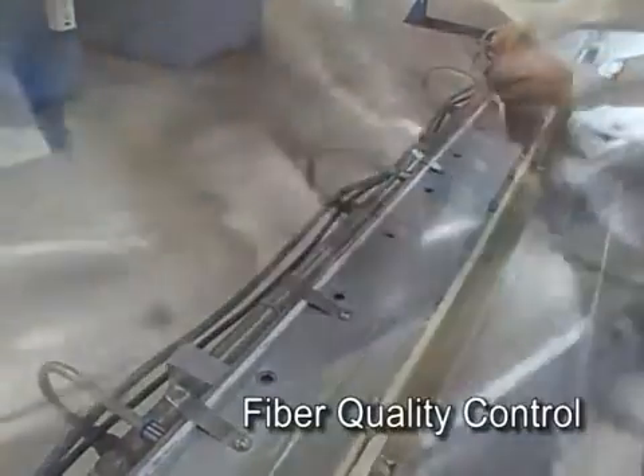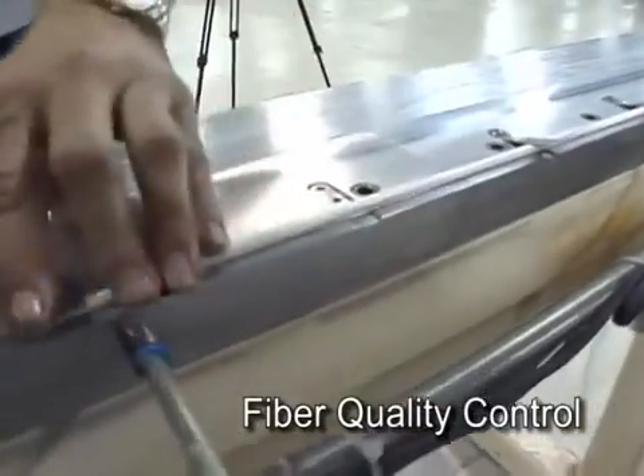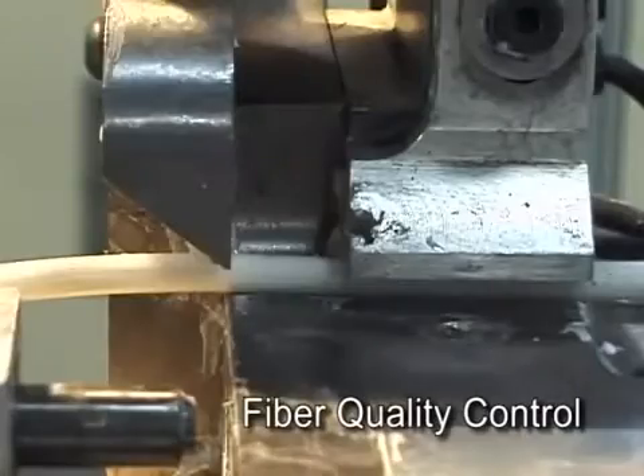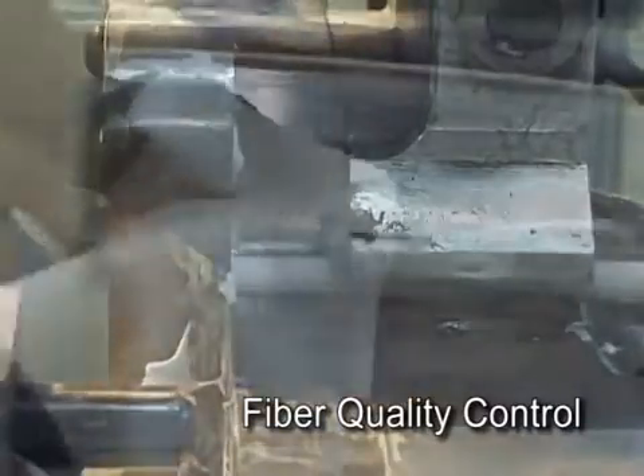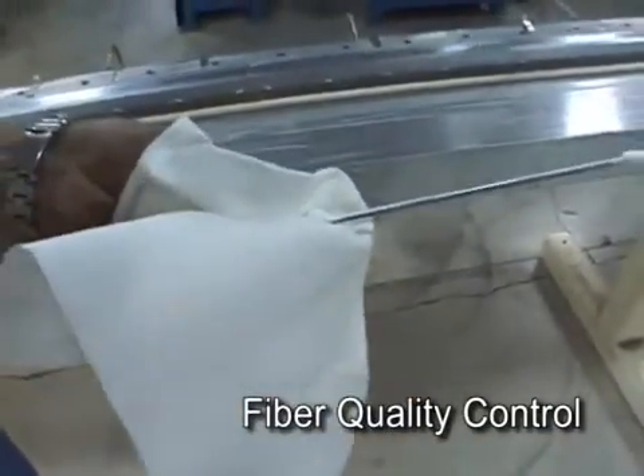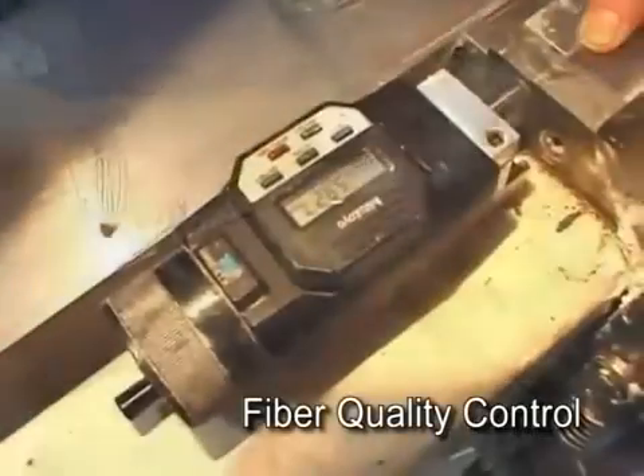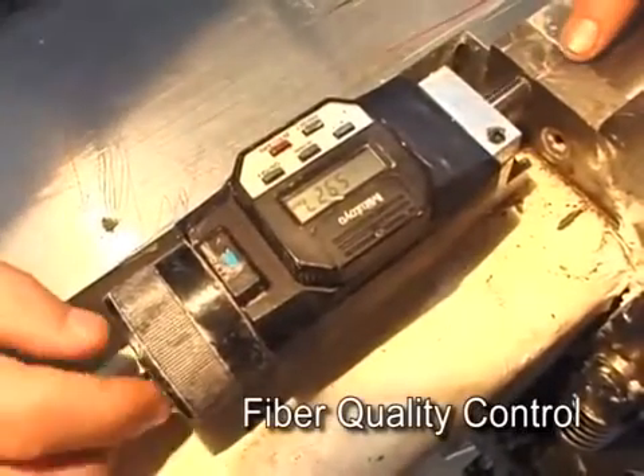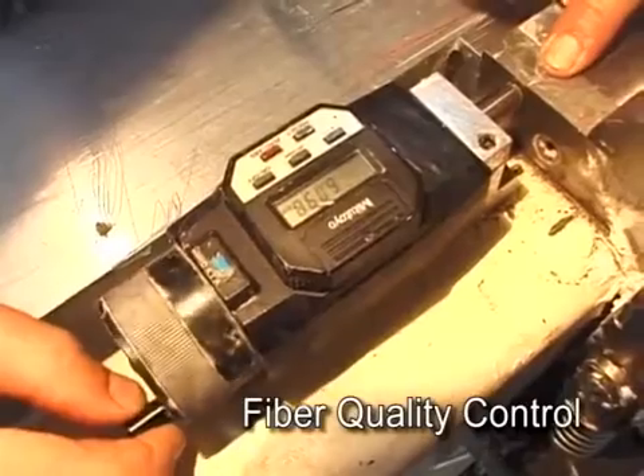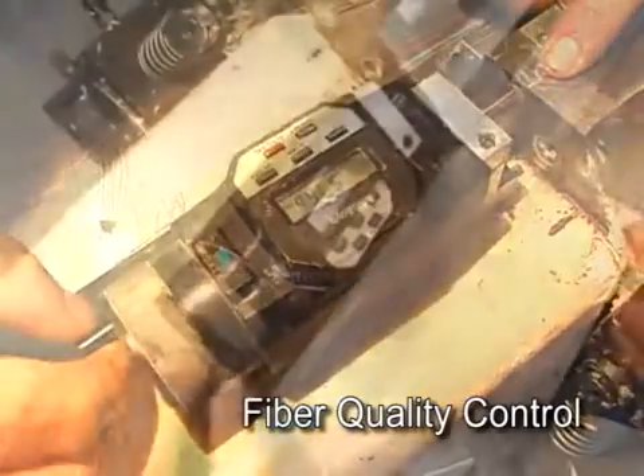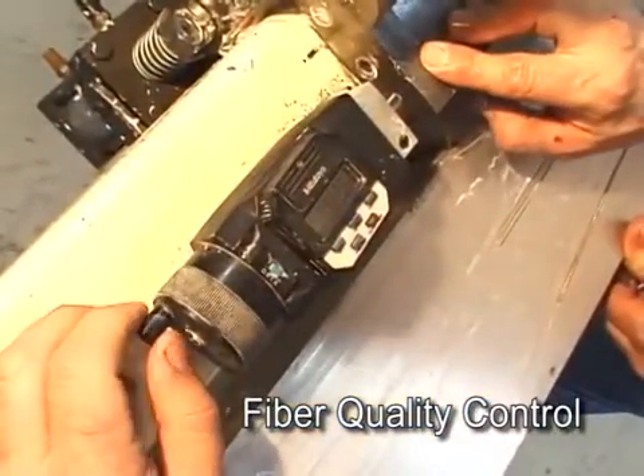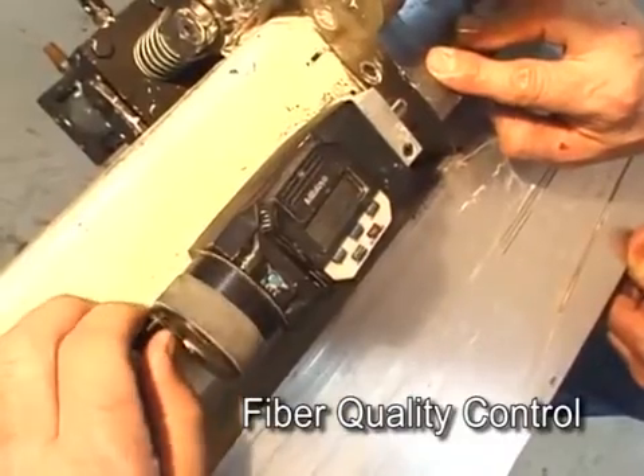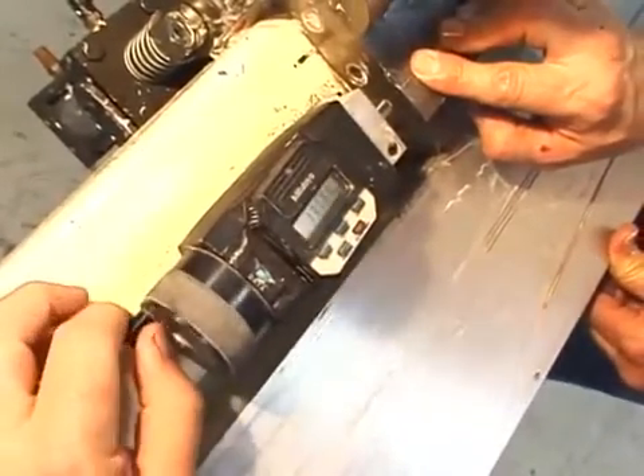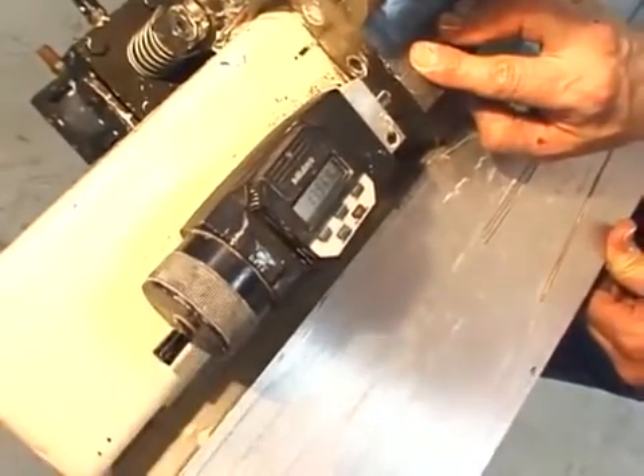To perform this test, a section of a tube is placed on a special test fixture that accurately cuts it to a predetermined length. The tube is opened midway along its length and the fibers are removed. One of the fibers is separated from the bundle and is mounted between a pair of measurement blocks. A micrometer wheel is carefully adjusted to just bring the fiber into tension. A digital readout displays the fiber length, which is then compared to the known length of the tube.